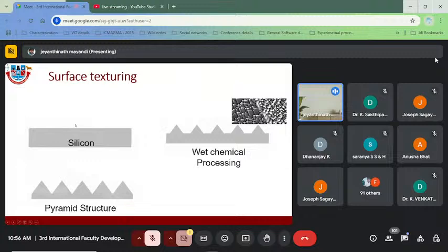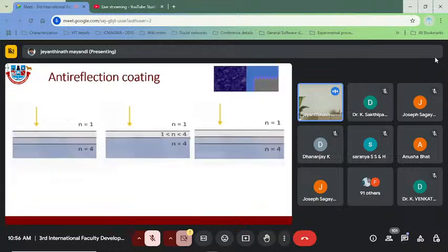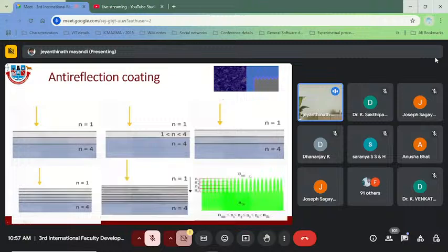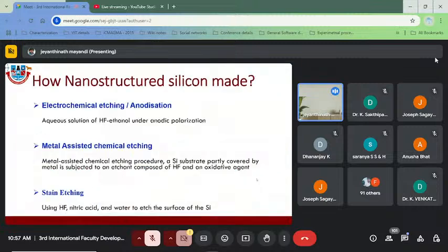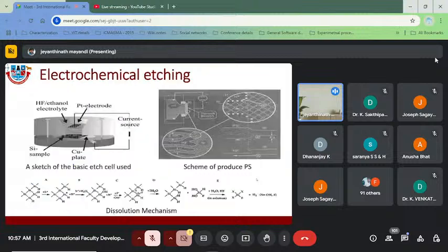So what we do is we take the silicon, and then maybe we make an N-type layer, and then we try to etch it using different types of etching to make these nanostructures, either nanowires, nanopillars, or hierarchical nanostructures, so that it could change the refractive indexes of the layers in a different manner. And we expect that we could absorb more light into the devices. This can be done by electrochemical etching, that is anodization, or metal assisted chemical etching, or stain etching.